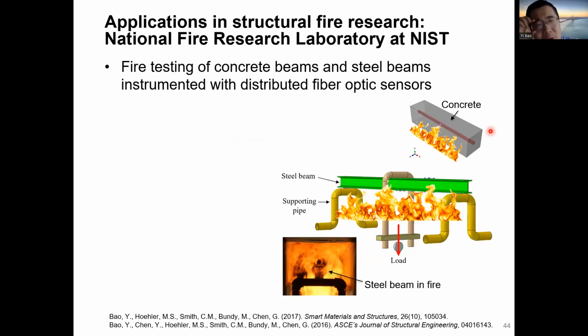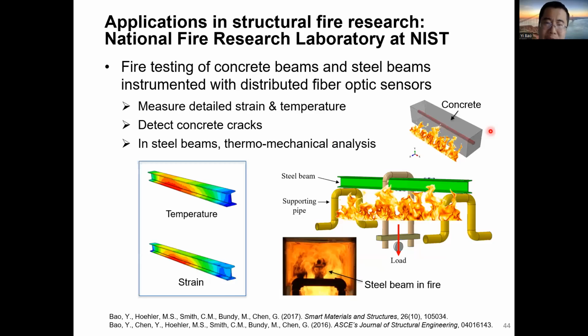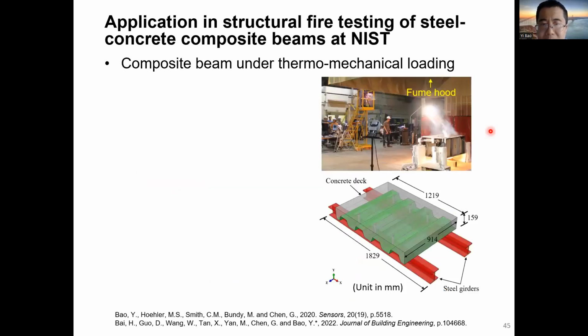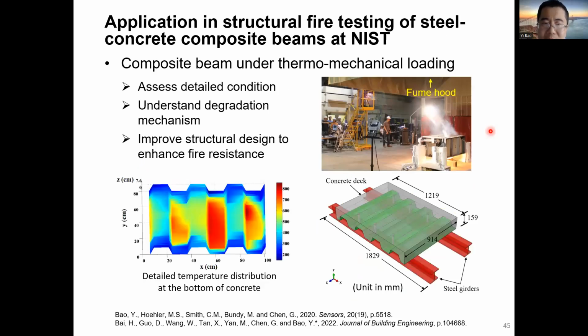Then based on this research, we applied the technology to fire hazard applications in the National Fire Research Lab. We have applied the sensor to both concrete and steel. So we burned the structures within fire, and we measured the temperature distribution for the concrete, steel, and steel concrete composites. This measurement was very important because based on the temperature measurements, we could conduct thermomechanical analysis more accurately without having to predict the temperature field.